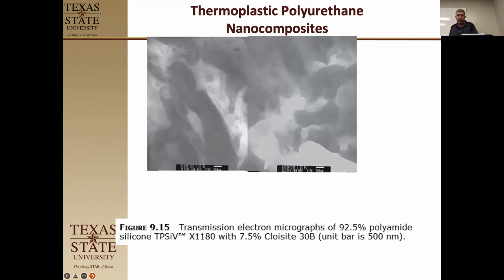All right. And so this is that with the montmorillonite. The other one was virgin. This is with the montmorillonite. You can see the montmorillonite aggregating in there. You can't really see it in these, but there is montmorillonite in the dark phase as well. So it's both suspended in the silicone phase and in the polyamide phase. And so it's actually pretty well dispersed in the system.